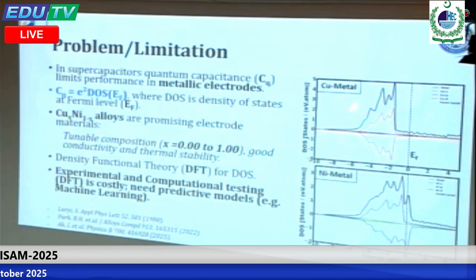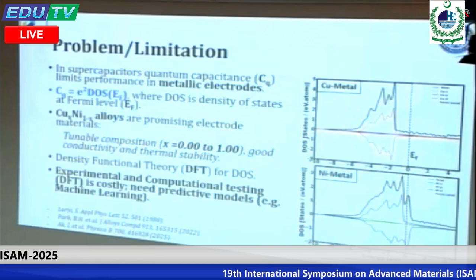Here is the density of states of pure copper metal. You can see that the density of states is a function of energy, in electron volts. At the Fermi level of copper the density of states is low, but at the Fermi level of nickel metal the density of states is higher. So we can tune this copper-nickel alloy system to a point where we get the maximum density of states, and in the end get a higher quantum capacitance.